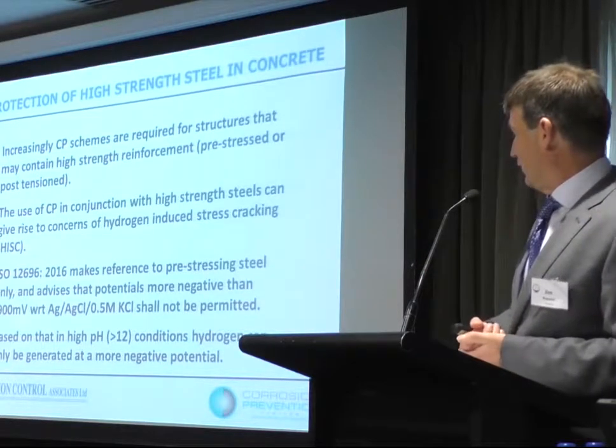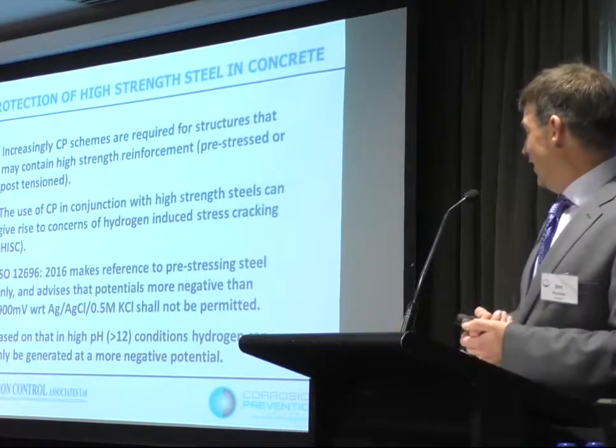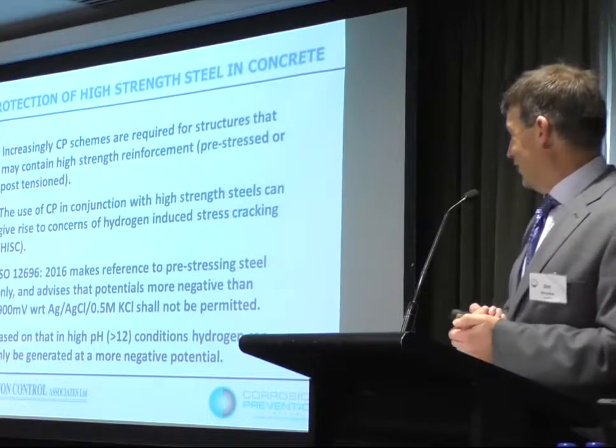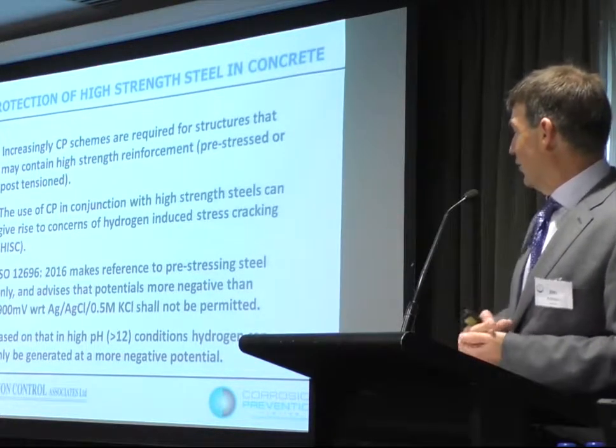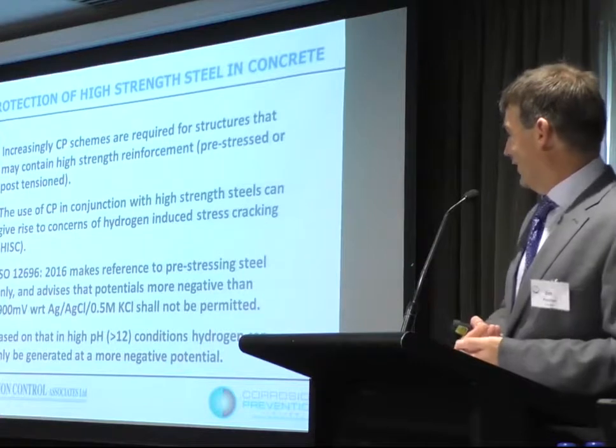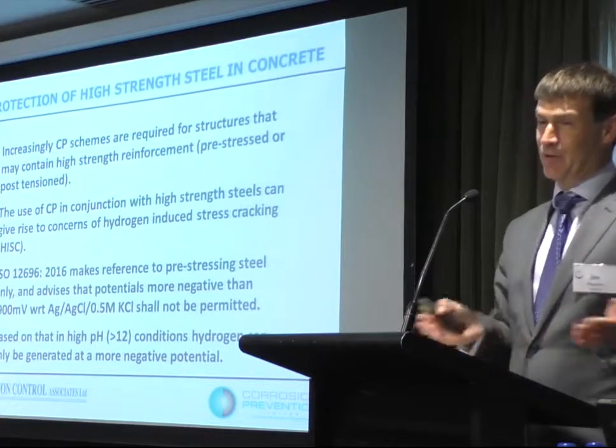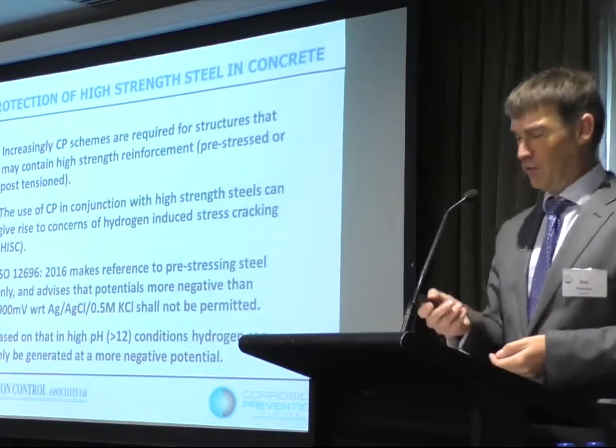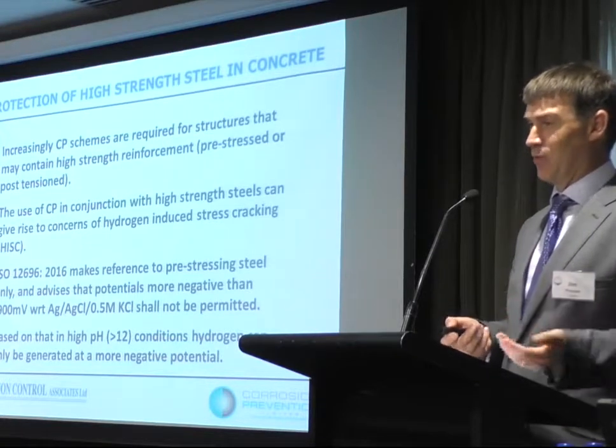This criterion is based on the fact that if you've got a high pH, we can't generate hydrogen on our cathode at a less negative potential. We can only generate hydrogen at a more negative potential than minus 900, so if we're keeping it positive of minus 900, we shouldn't have a problem with hydrogen evolution, so we shouldn't have a problem with embrittlement.